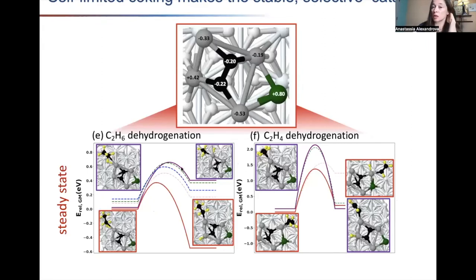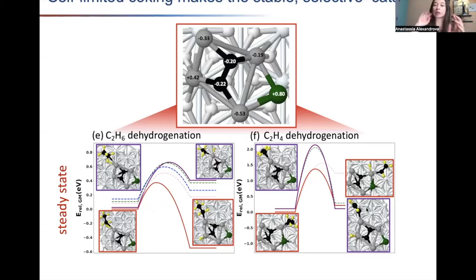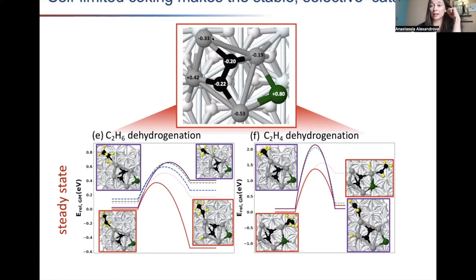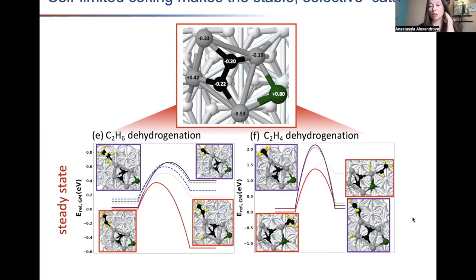We asked Scott: we think there is carbon in this system — can you measure it? He measured, and both Pt4 (which cokes) and Pt4Ge show a substantial carbon signal, but Pt4Ge retains ethylene binding sites. If we look at the activity of this carbon-embedded cluster, it is very good at dehydrogenating ethane, but dehydrogenation of ethylene is harmed — most profiles would not dehydrogenate. What we conclude is that this partially coked cluster is unable to coke further — it's self-limiting coking.